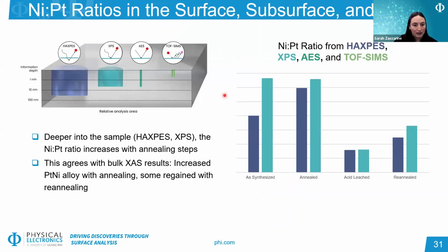So we're going to wrap up by looking at the trends in the nickel to platinum ratio that we got from each of these different techniques. Starting with HAXPES in this dark blue color, which is our deepest sampling depth out of these four techniques, we see with annealing an increase in the nickel to platinum ratio. So again, that means that the nickel from the nanowire core is moving towards the surface, and or platinum is slightly moving towards the subsurface. So we ultimately are getting an increase in nickel relative to platinum with this annealing step, which was designed to alloy the platinum and nickel together.